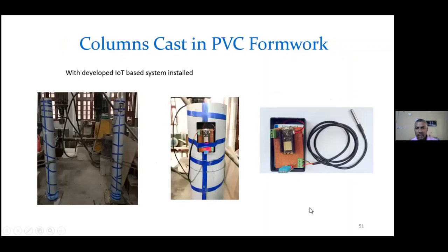So this maturity relation is not the same as the one I showed you last time. There is a difference because it is developed only from the data of 0 to 72 hours. Now you can see some of the columns we have cast in PVC formwork. This is in our laboratory, and while casting, you can see the small instrument that we have put here, the IoT based system. A closer look shows this instrument in a casing.